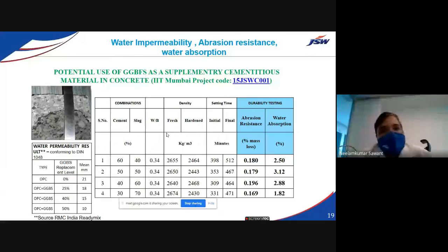Water impermeability, definitely, is a major concern wherever the RCC consultants are advising the contractors, builders and infrastructure companies. So water impermeability and abrasion resistance should be there. If I am using cement and slag, and this is the water binder ratio, you can see cement at 60% and 40% replacement, and a combination of 50-50, then 40-60 and 30-70. The water binder ratio we are keeping at 0.34. You can see the durability testing, abrasion resistance, as well as water absorption. These are good whenever we do the OPC replacement with 50%.